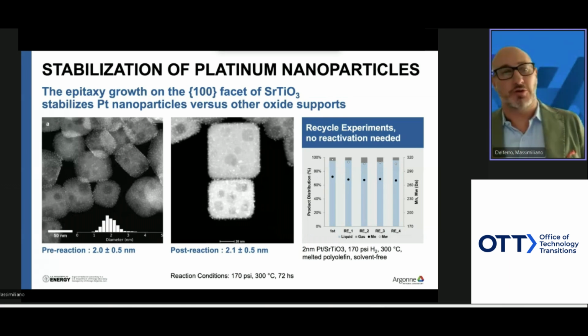As I mentioned before, we chose to use a perovskite, in this case strontium titanate with platinum, because there is a very strong surface nanoparticle interaction called cube-on-cube epitaxy. And because these reactions are conducted at high temperature and high pressure, on a normal support like silica alumina, the platinum nanoparticles tend to deactivate very fast, losing their chemical and catalytic properties. But because we have this cube-on-cube epitaxy, the platinum doesn't move on the surface. In fact, this is an example on the right of the slide where we repeat the reaction. We just add fresh polymers, and you can see the catalytic performance doesn't change with time.